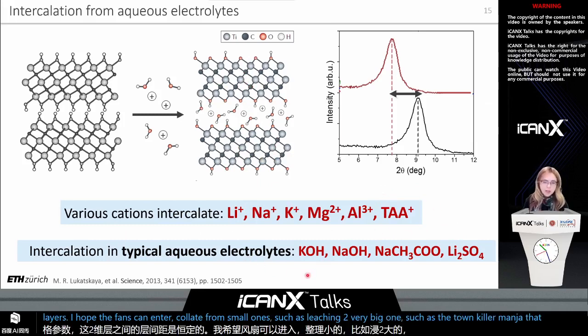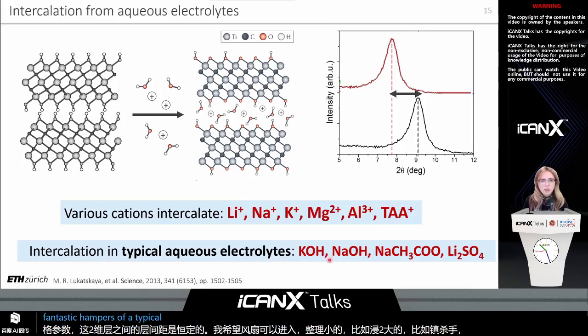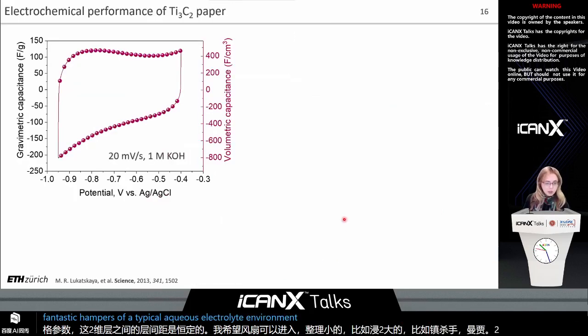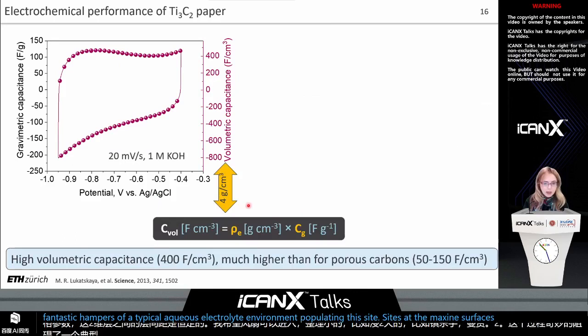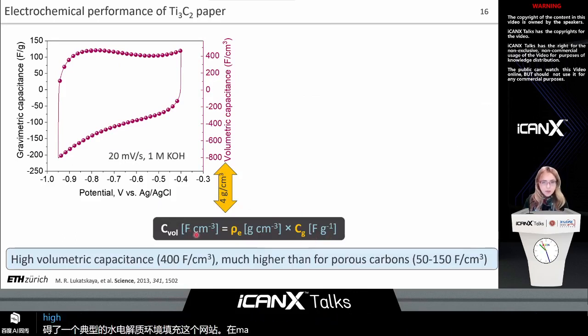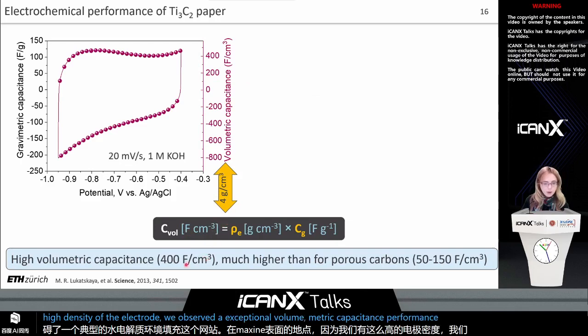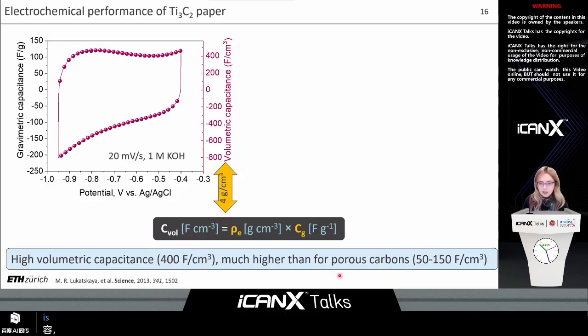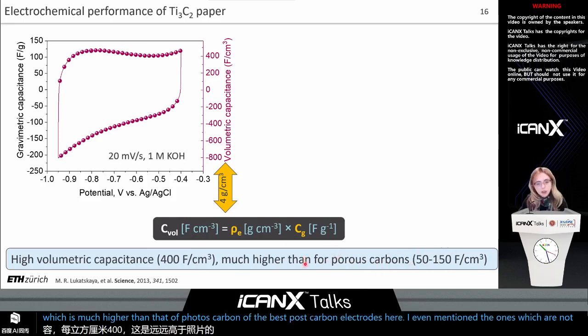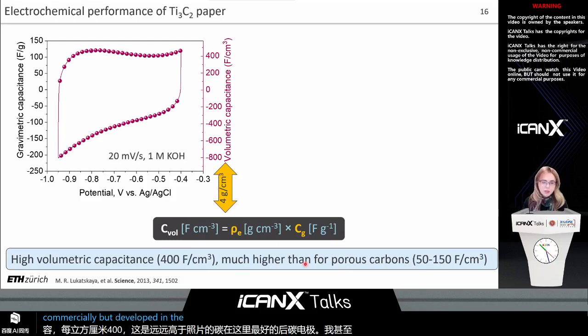The process spontaneously happens in the typical aqueous electrolyte environments, prepopulating the sites at the MXene surfaces. Since we have such high density of the electrode, we observe exceptional volumetric capacitance performance of 400 farads per cubic centimeter, which is much higher than that of porous carbon, of the best porous carbon electrodes. Here I even mentioned the ones which are not commercial, but developed in the labs with a specific focus of